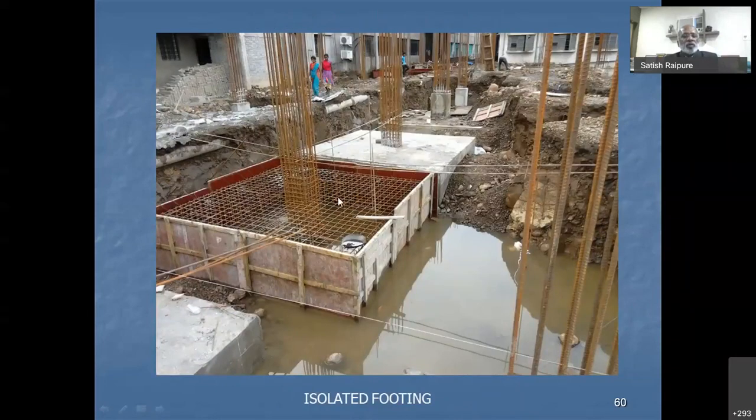This is an actual photograph of an open footing. In case the depth is more than say 600, we always recommend providing nominal reinforcement at the top, so that it will prevent any shrinkage cracks that will develop at the top. And concreting should not be done in water-filled pits like this. You will have to dig one more sump here and drain out the water, till the concreting and even after the concreting, till it gets set, you will have to remove this water. And then only this concrete will get the desired strength, otherwise not.